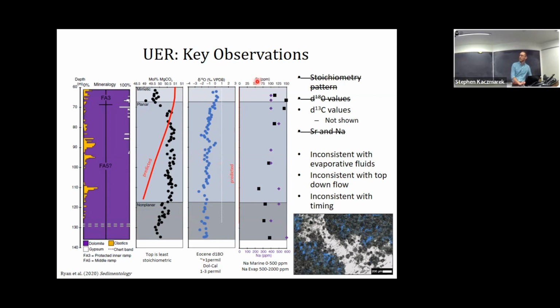And then in terms of trace elements, strontium and sodium, we would expect values for marine dolomites that are sort of in the range we observe, whereas evaporitic dolomites tend to have much higher values than we observe. So our stoichiometry pattern, our stable isotopes, and our trace element concentrations don't really fit with this story of top-down evaporative reflux of these fluids.